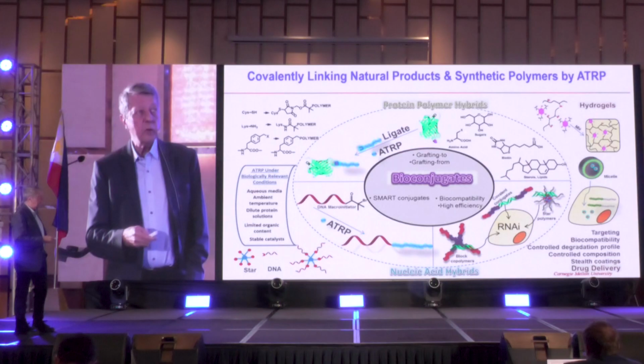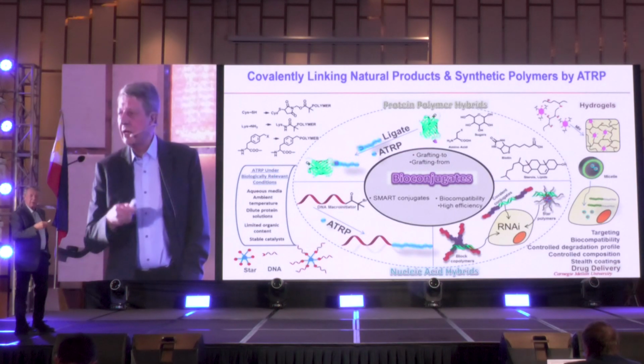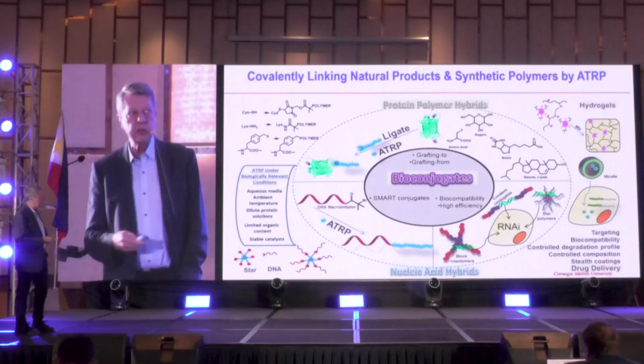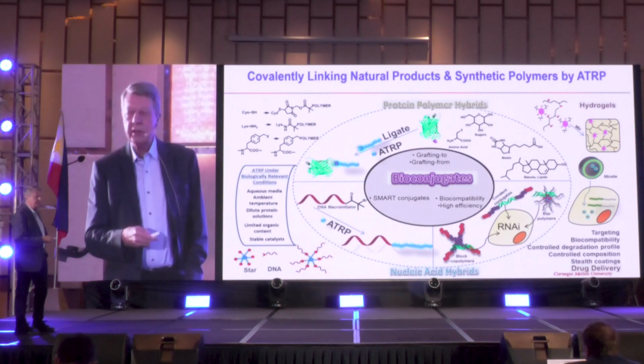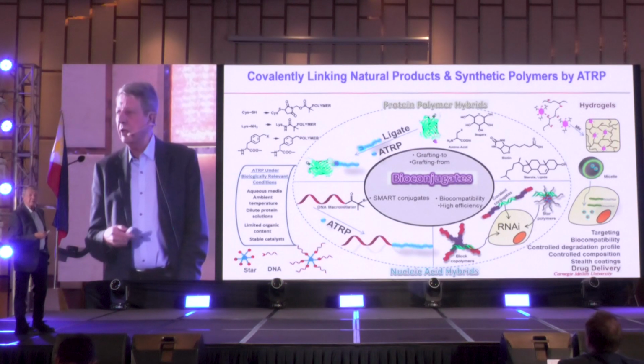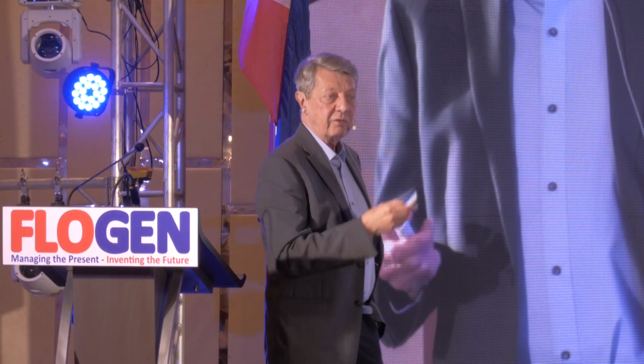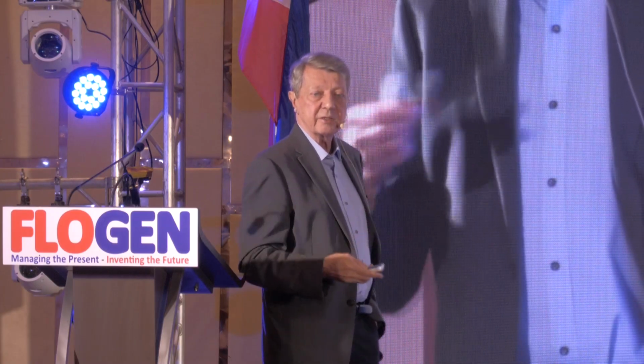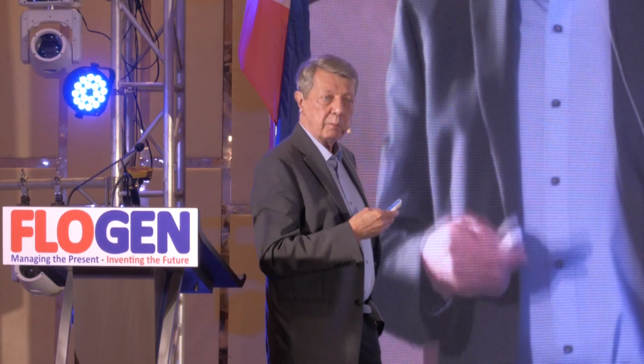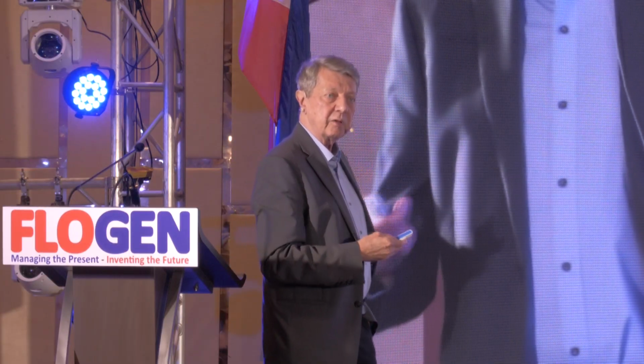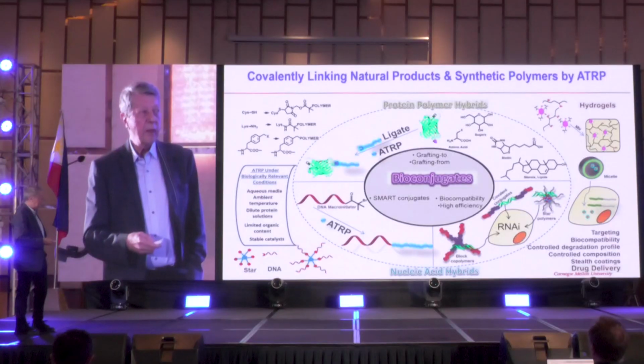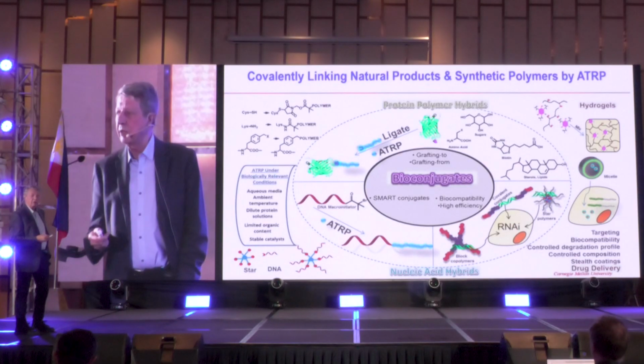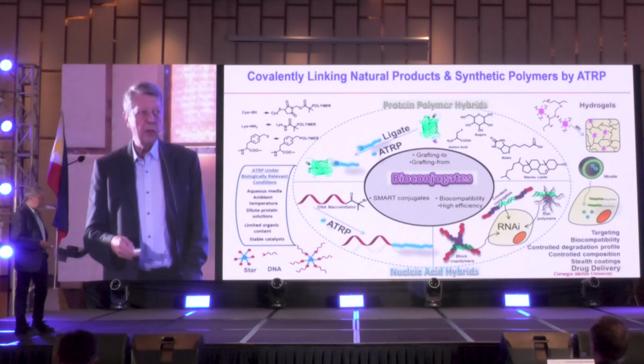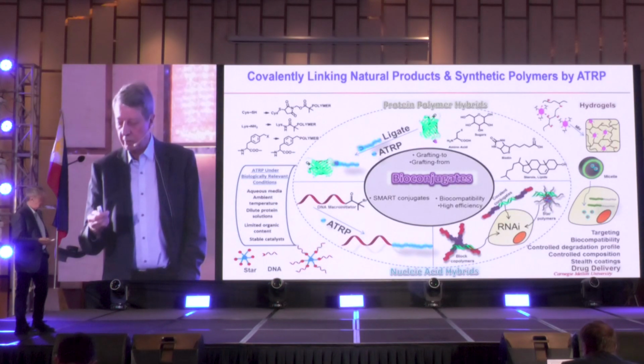Alternatively, you can put a functional group, this atom transfer radical polymerization initiator, and then you add monomer and catalyst, and you grow practically the same polymer. And then by dialysis, you remove catalyst and unreacted monomer. So this is a much more feasible and much easier reaction. And also you can conjugate in a similar way nucleic acids, DNA or RNA. You can make polyplexes. You can conjugate practically with any kind of biomolecule.